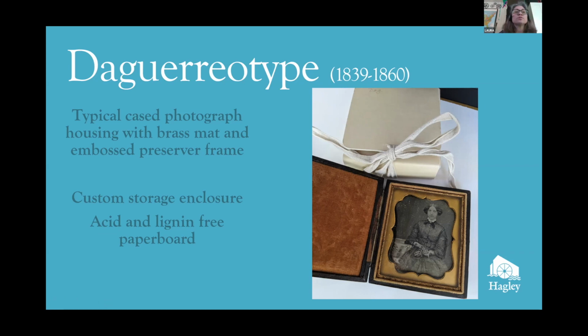The image can be obscured if the metal plate becomes tarnished. This can occur if the sealed case components are compromised. However, you should never attempt to open a case to remove the daguerreotype. Also, you should not attempt to clean tarnished plates. Touching or brushing of the image surface can cause permanent scratches, and commercial chemical silver cleaners also leave sulfur residues that are nearly impossible to rinse away. These sulfur residues create complexes with the silver, and they turn into blemishes over time.